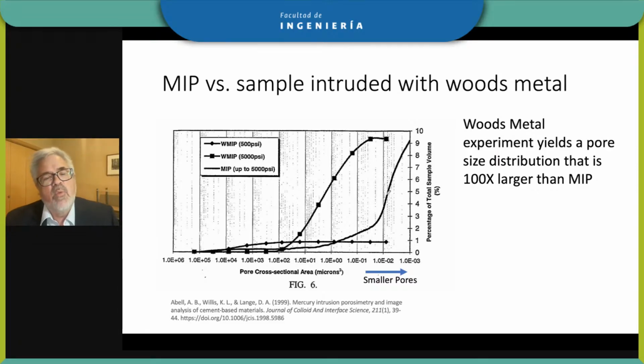But what happens is that if we use a scanning electron microscope to look at these and physically measure the sizes, they're very different from the calculation by the physics of the intruded Woods metal. And so our insight here is that these pores inside the microstructure are considerably larger than we would have expected by the physics. And this helps us relate the two experiments to each other. So knowing this, we can design materials to have a different pore distribution, where we have more smaller pores, fewer larger pores, and therefore stronger materials.